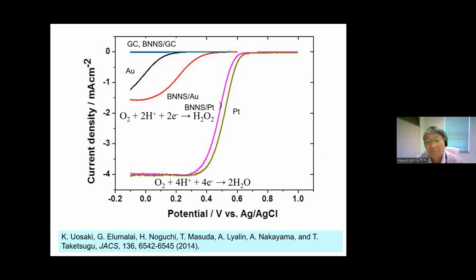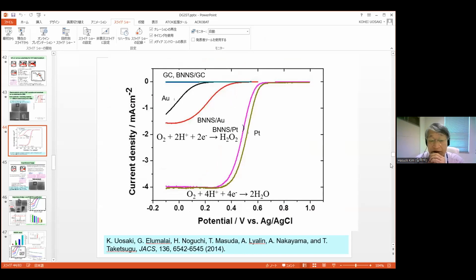The theoretical calculation shows, of course, boron nitride itself is a very wide gap insulator, but if it is put on platinum, gold, or nickel, then through the modulation, or the bending of the boron nitride, the interaction makes a new state within the energy gap. Okay. Thank you. Any other questions? Not only from students, but also from professors this time.